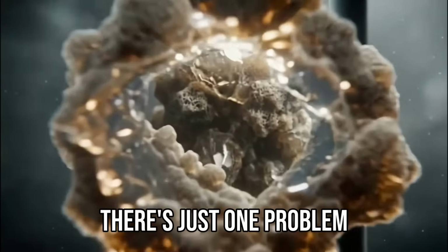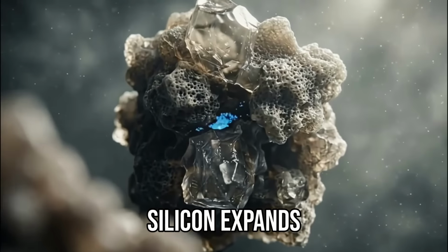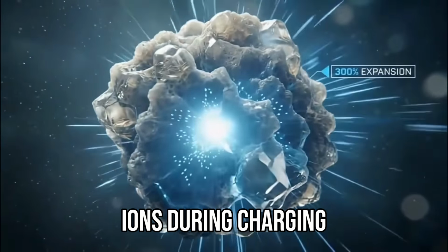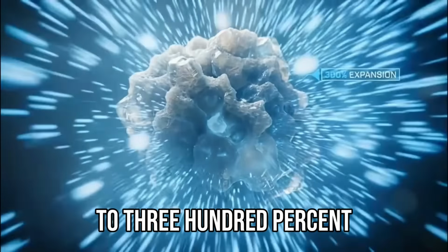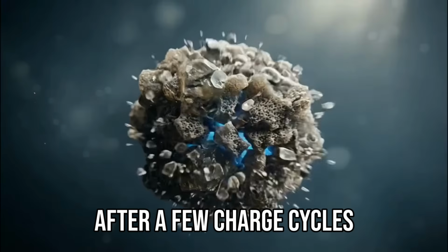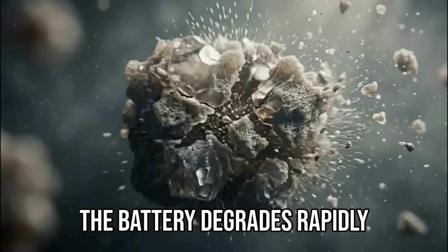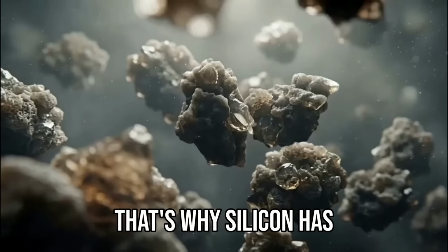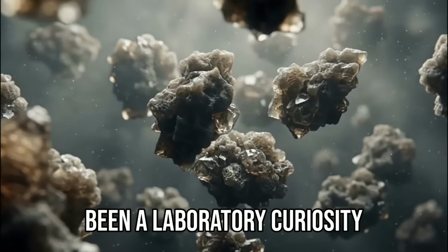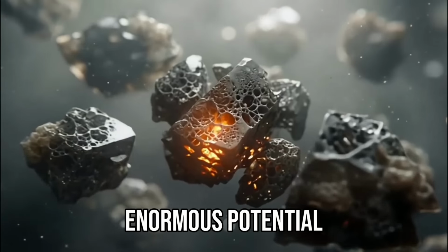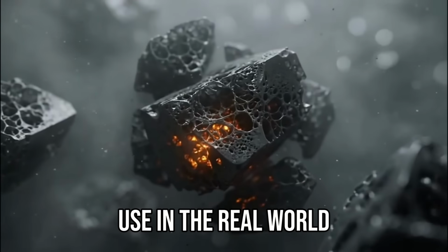There's just one problem. Silicon expands. When it absorbs lithium ions during charging, it swells by up to 300%. After a few charge cycles, it cracks. The battery degrades rapidly. That's why silicon has been a laboratory curiosity for decades. Enormous potential, but too unstable to use in the real world.